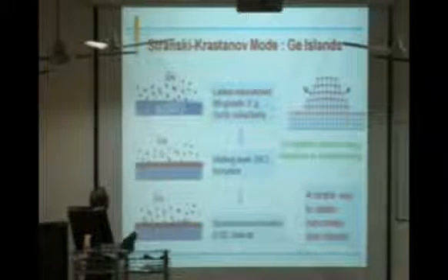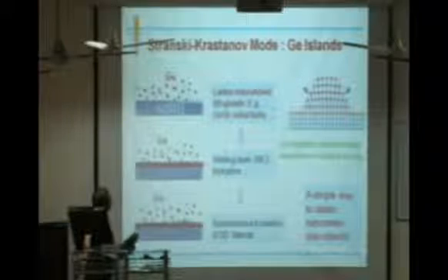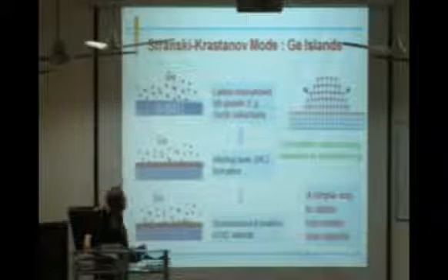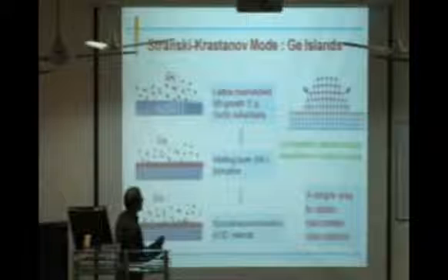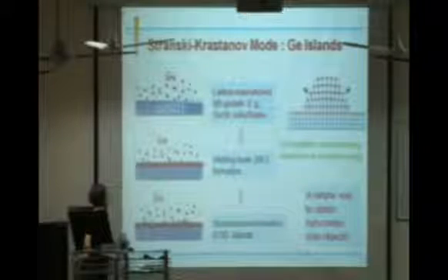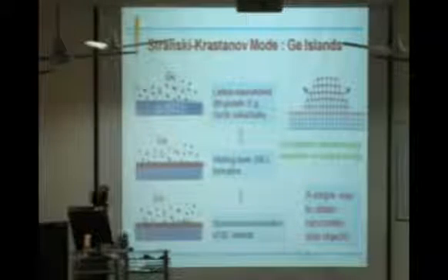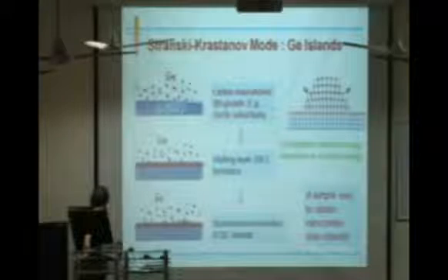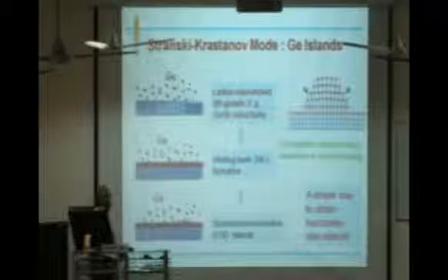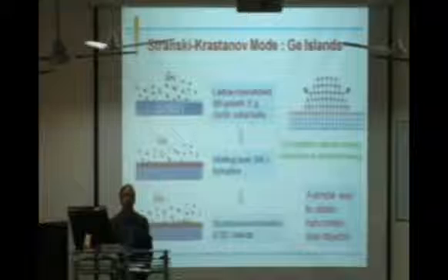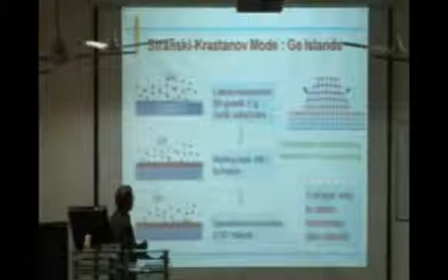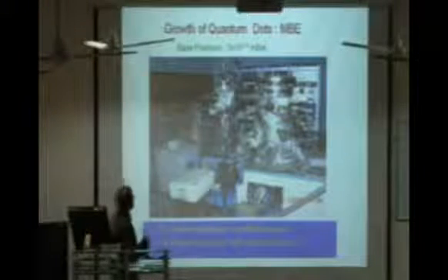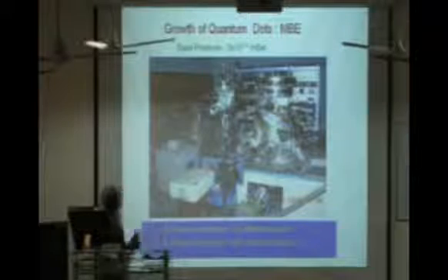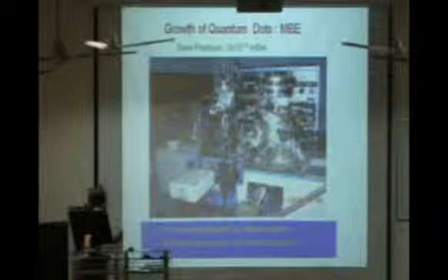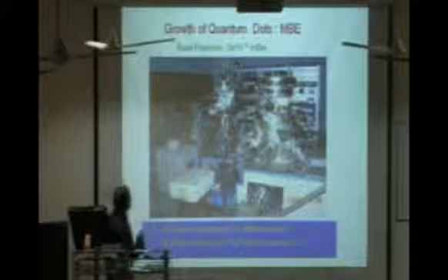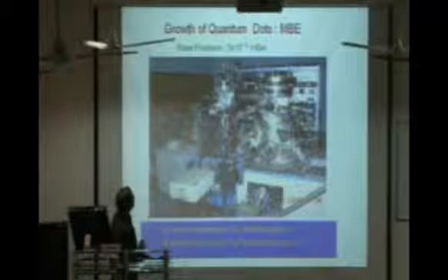But as you grow the lattice mismatched material, a lot of strain energy builds up. There is a competition between the elastic energy and the surface energy. And finally, thermodynamically it will be stable if it makes this kind of pyramids or dot-like structures. Those are more stable. The system that we have in our Kharagpur lab is called molecular beam epitaxy. This is a very old system we have had for about 20 years.